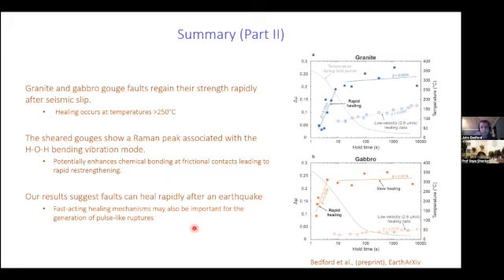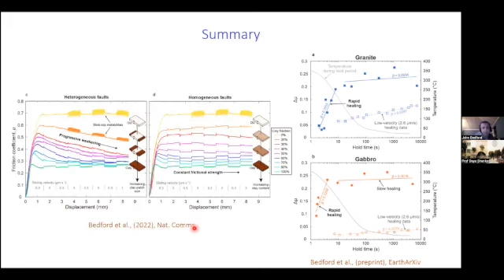But I'm almost done. I'll just leave you with, I'll bring back the other figure from my first part of the talk, just to summarize that. In the first part I showed you the long-term steady state strength evolution of faults, and how heterogeneities can really affect that and make faults much weaker and also more unstable than compositionally equivalent homogeneous faults. And in the second part of the talk, we looked at high velocity friction data and how the strength is recovered after high velocity slip, and we see this rapid healing, which is potentially associated with chemical changes that occur during high velocity slip.